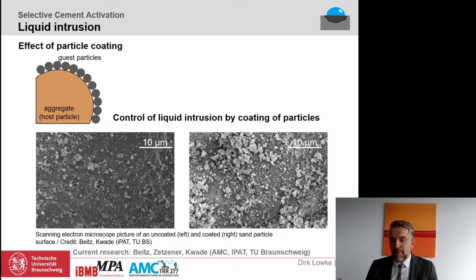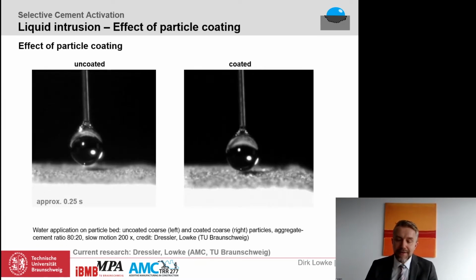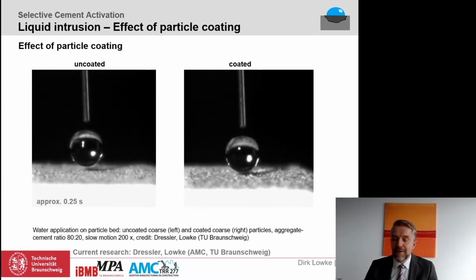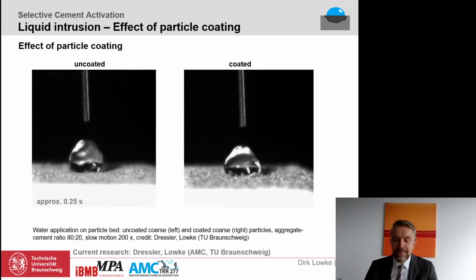And one really promising way to do that is the coating of particles. Therefore, our co-workers from the Institute of Particle Technology coated sand particles with a hydrophilic silica fume. On the left side, you can see the uncoated sand particle, and on the right side, there's the coated sand particle. And now let's see how this coating influences the penetration behavior. Again, on the left side, the uncoated particles, on the right side, the coated particles.